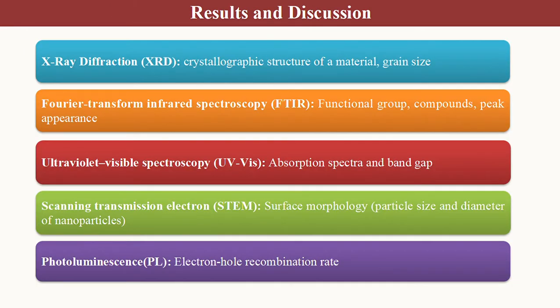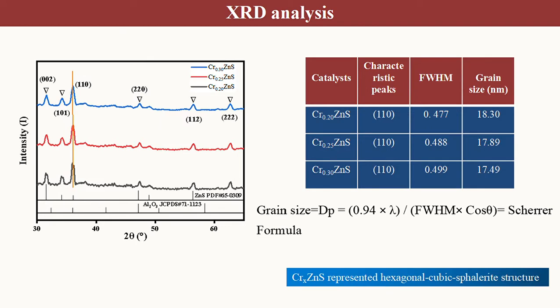The crystallographic structure of a material, grain size, band gap, functional groups, peak appearance, and electron-hole recombination rate were observed by these characterizations. The XRD results of the samples are shown in the figure. The diffraction peaks were found at 2 theta located at different angles.